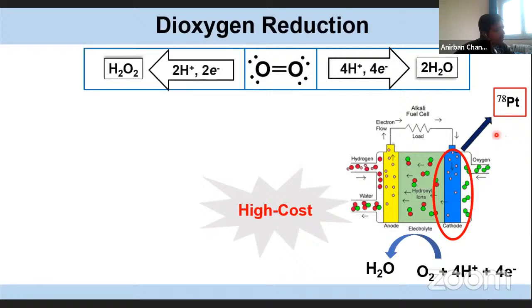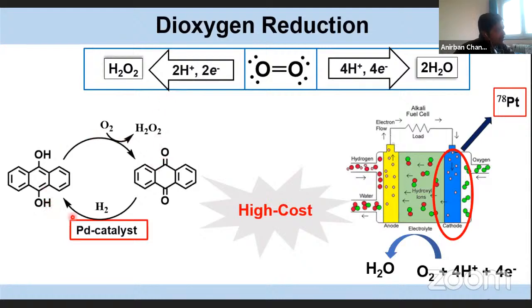Another way of oxygen reduction is two electron reduction of oxygen to hydrogen peroxide, and it is also very significant because hydrogen peroxide can be used as an alternative energy carrier because of its high energy density at ambient temperature. It is also an environmentally friendly oxidant and also important because of its delignification efficiency. But if we look at the industrial production of hydrogen peroxide via the anthraquinone method, it needs a palladium catalyst for the effective formation of this catalytic cycle. And again, the presence of the palladium catalyst increases the cost of the production.